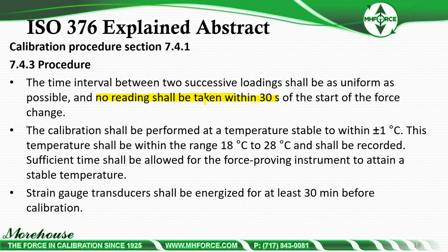So to do a calibration with ISO, a lot of times that machine will not be capable of doing that calibration because you actually have to hold the force for at least 30 seconds at each test point. ASTM does not address this. We've adopted for all of our calibrations, because it's just general good measurement practice, to take at least a dwell time of 30 seconds and then start taking the readings, especially with static force.